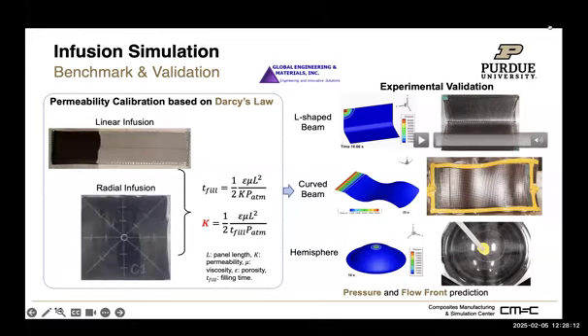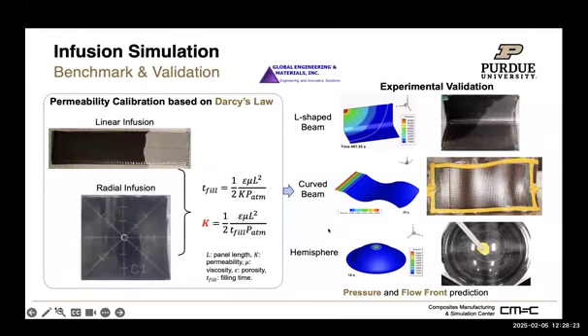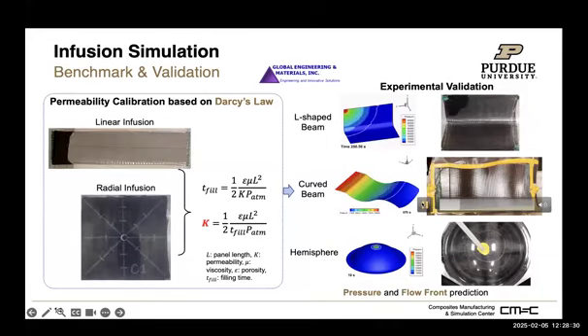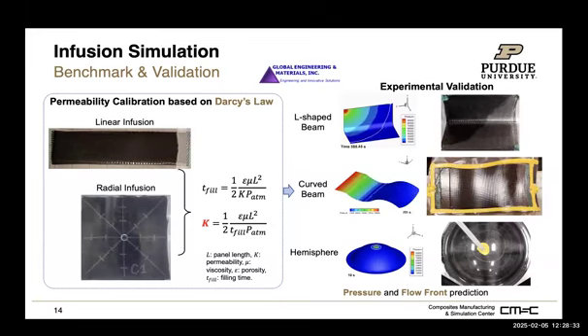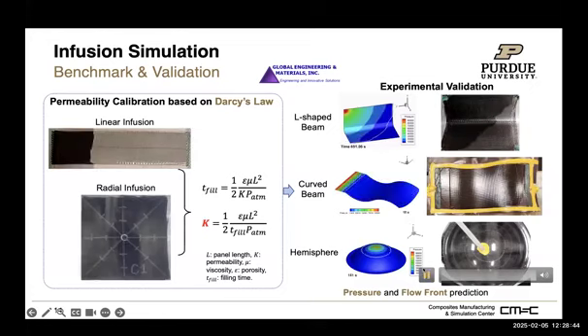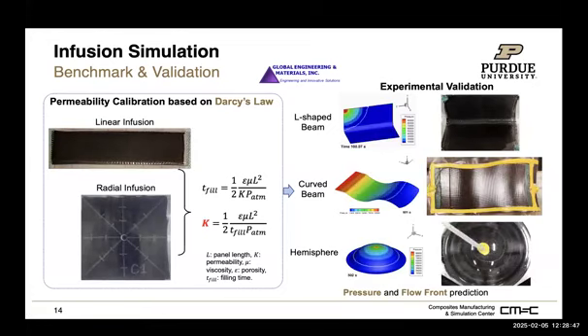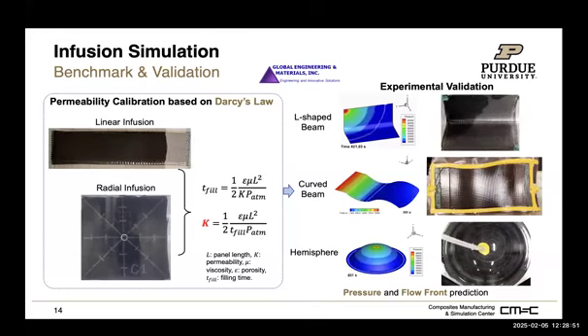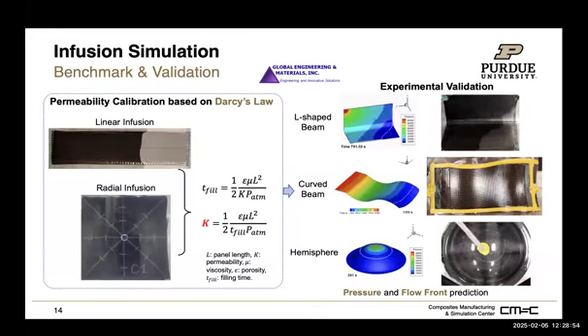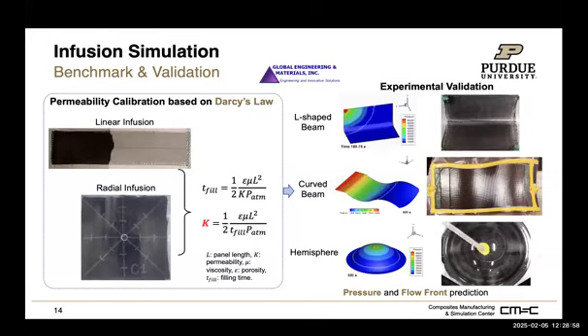Then we also run a benchmark study to simulate cases such as this L bracket, the one I show in the middle, which is the simulation of flow for a doubly curved mold, and the infusion for a semi-hemisphere shape, like a dome shape. Once we validate those simulations using the results from the fabric characterization, the next step is that we want to explore further.